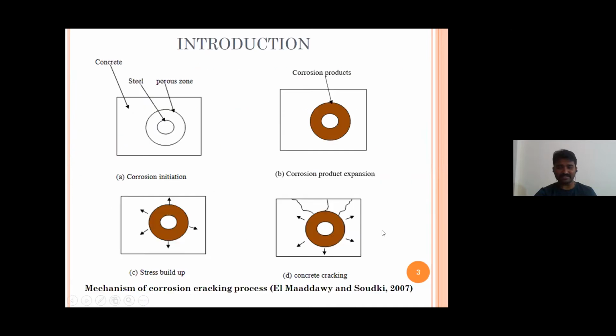If you see the service life prediction, let me explain this one. Once the corrosion initiates, until the complete porous zone thickness is filled up, there will not be any expansive pressure. Once it is completely filled, then only it starts exerting expansive pressure and we start noticing severe cracks like this. After that, there will be spalling and all. These figures are courtesy of El Maaddawy and Soudki.